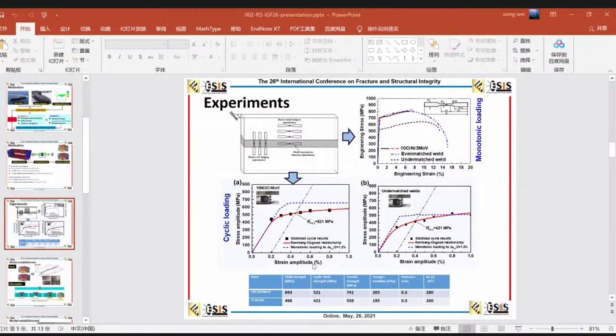So for the experiment, the basic mechanical properties of the materials are presented in this page. So we used the base metal of about 700 megapascal, and the undermatched weldment is about 500 megapascal.